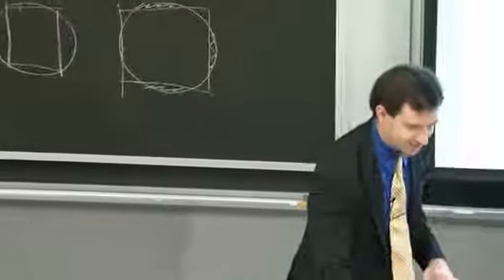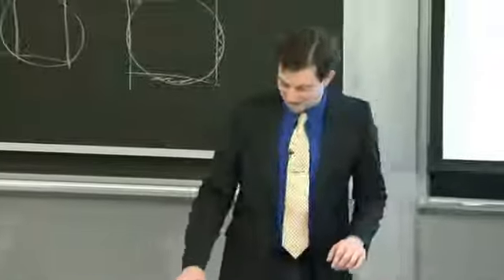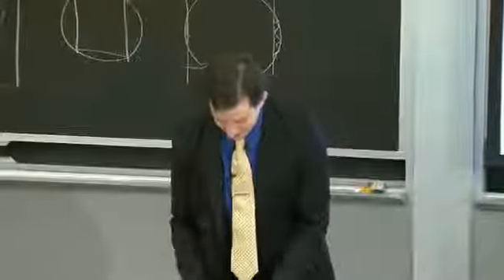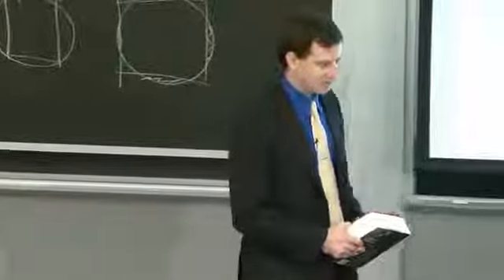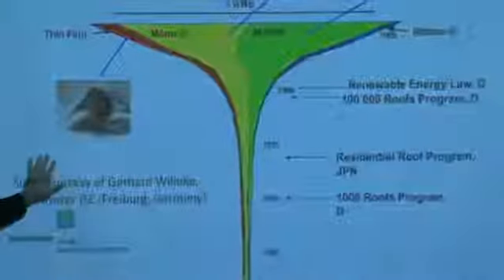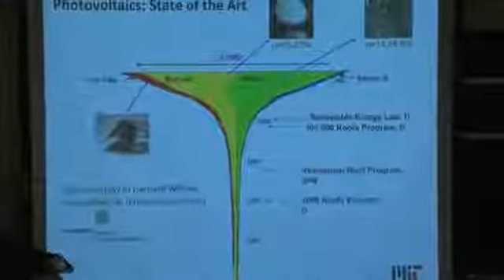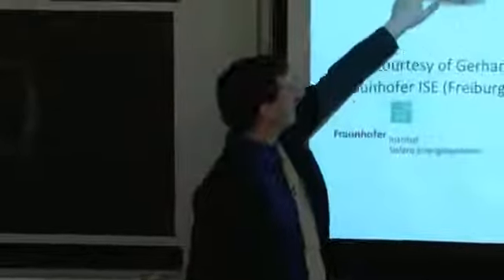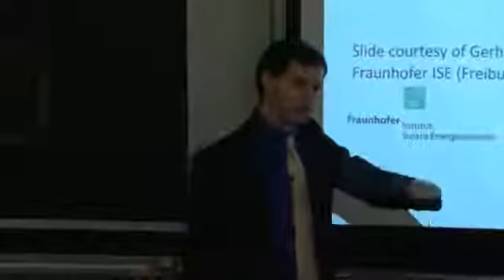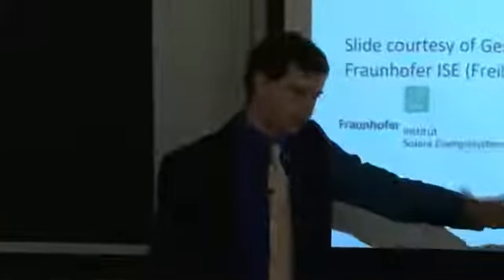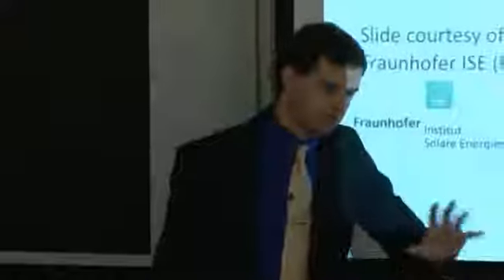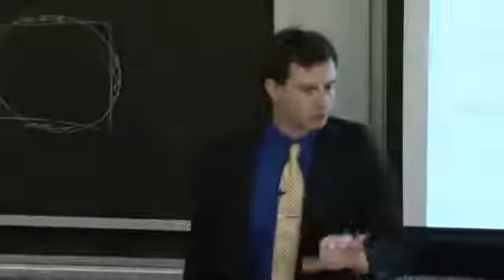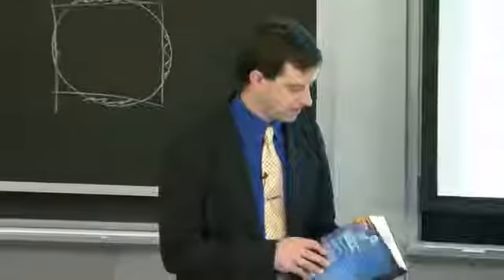And is there microcrystalline? There is also microcrystalline silicon. And microcrystalline silicon is actually at the phase transition between amorphous and polycrystalline silicon. So as you're going from an amorphous material, increasing the temperature of growth, or increasing other parameters during the deposition process, as you begin to evolve from an amorphous material into a crystalline material, you transition through this microcrystalline regime, which is a bit of a hybrid, has some regions that are amorphous and other regions that are crystalline.